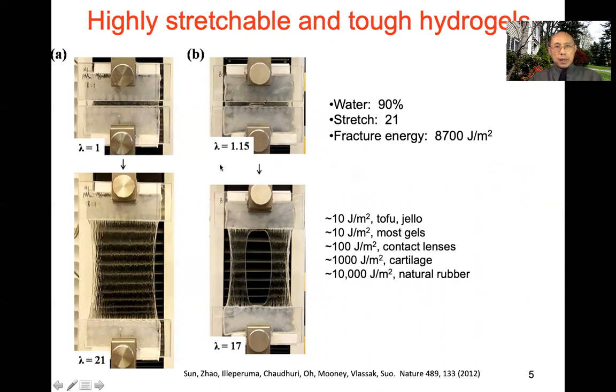Very tough material. In order to measure toughness, fracture energy, we also use a blade to cut a crack and then stretch 17 times. The crack does not grow. Instead, the crack becomes a hole. This corresponds to very high toughness, and this measurement gives us a high toughness of this value. Now let's put this high toughness into context. For tofu and jello, the toughness is about 10 joule per meter squared. Most gels have this value.